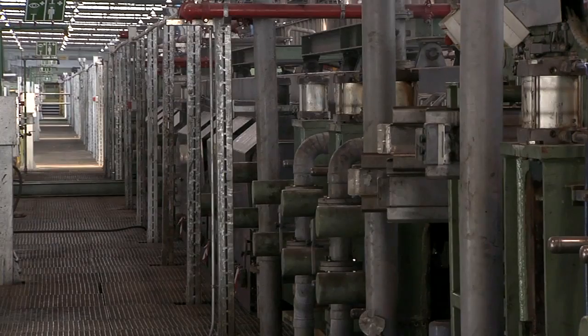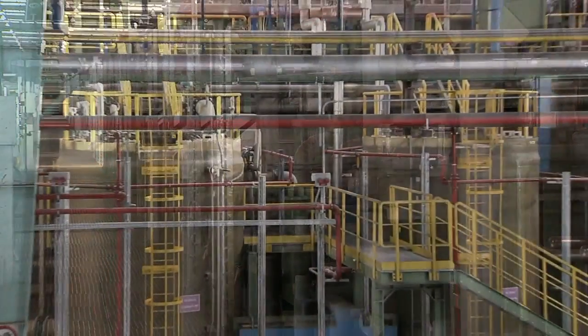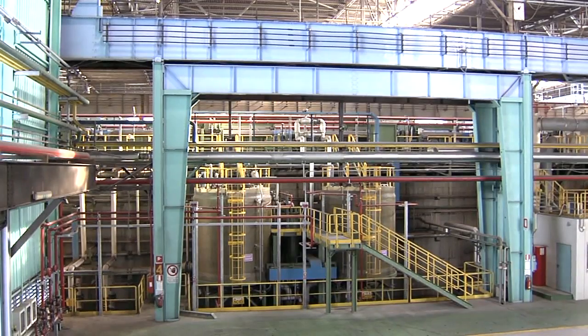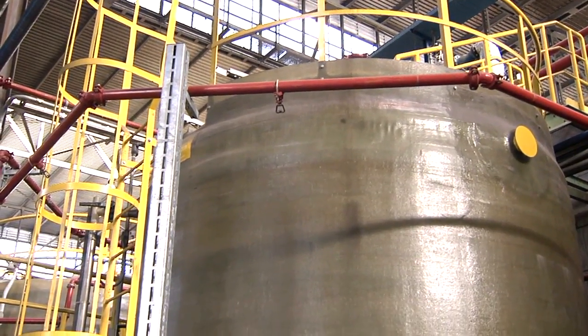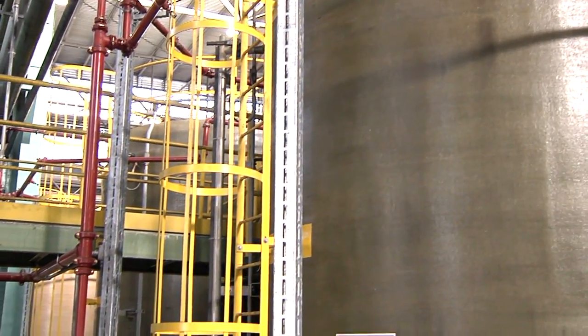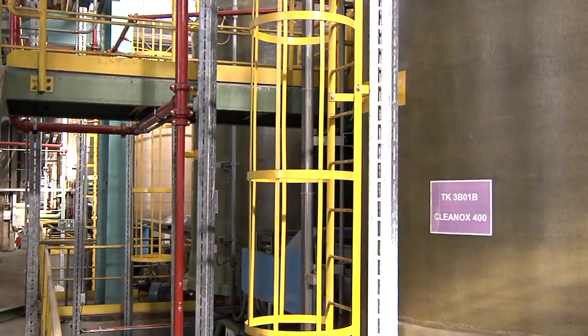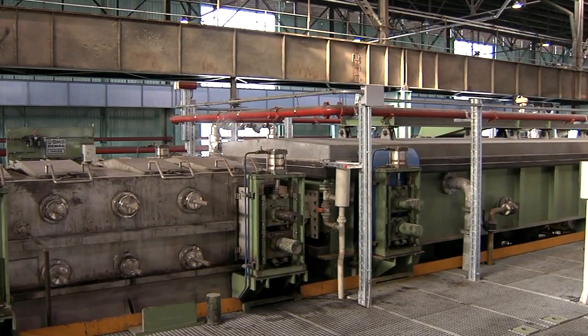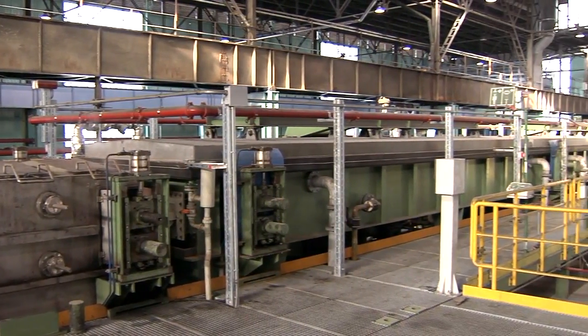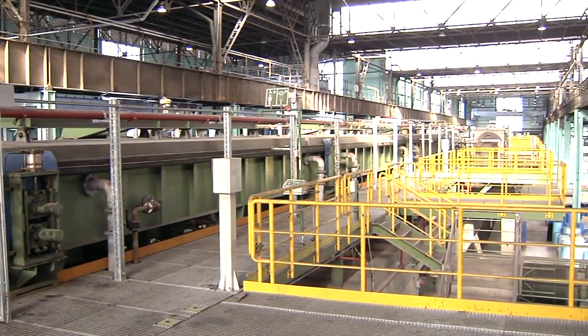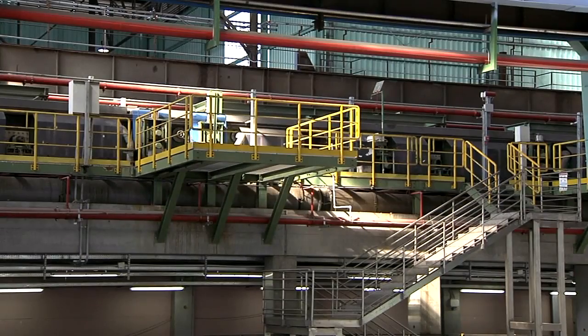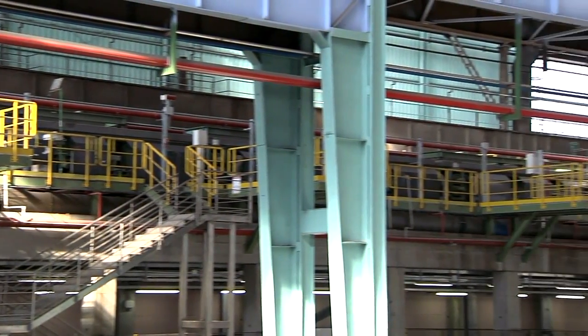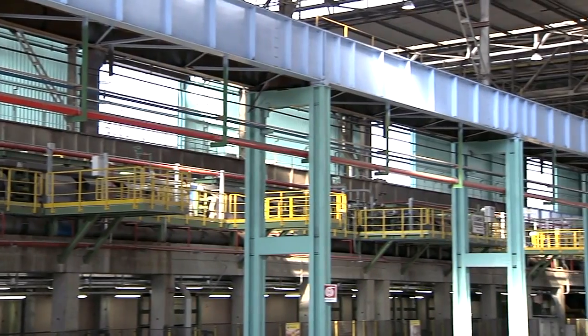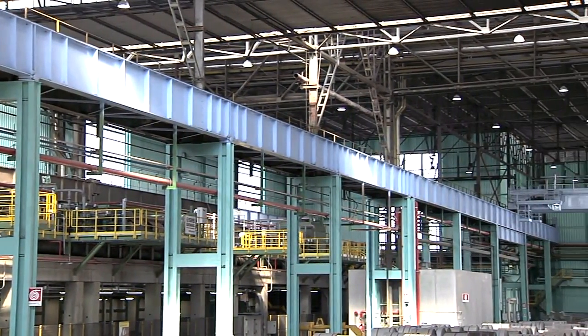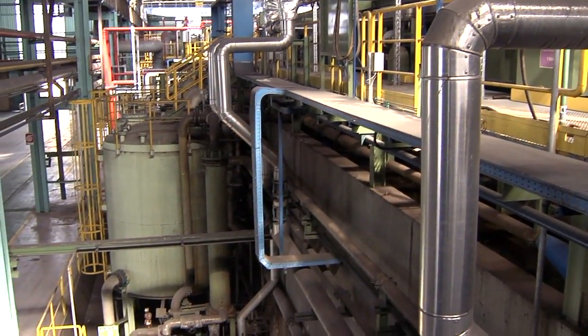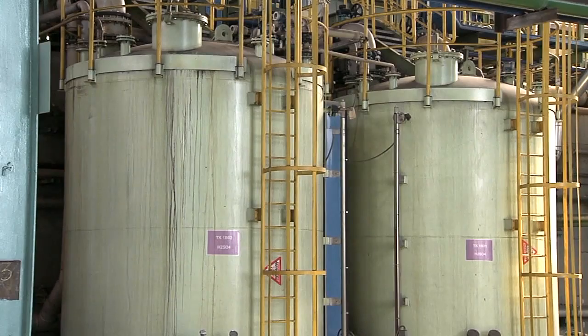2 intermediate rinsing units with brushing machines. The strip then enters the spray pickling unit. Owing to the strict environmental requirements, a special pickling agent is used here. As the strip runs through, it is exposed to the action of acid from both pickling lines for a good 90 seconds. Every trace of scale is removed during this time. The pickling acids are reconditioned and reused.